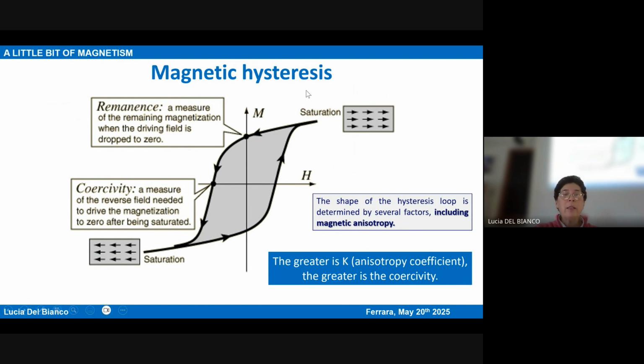And to annihilate this remanent magnetization, to reduce it to zero, you must apply a negative field, which is called the coercivity. And then you can close the loop if you like. You have a hysteresis loop, a magnetic hysteresis loop.